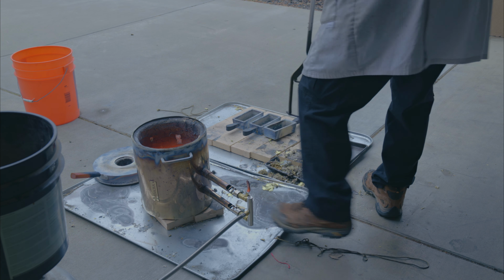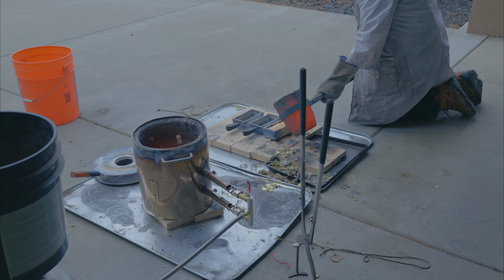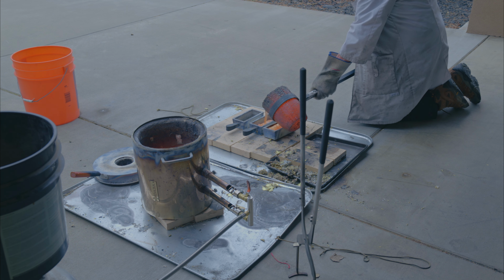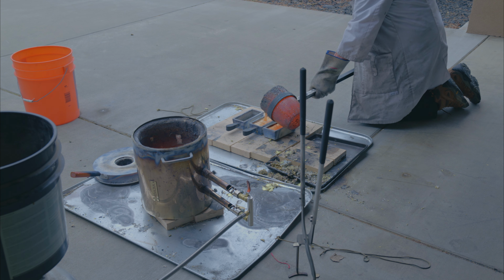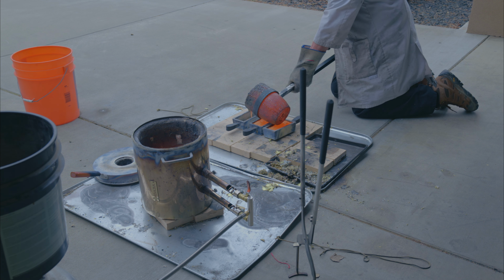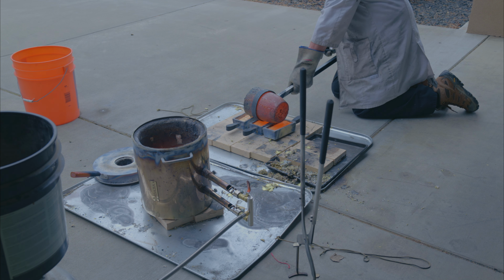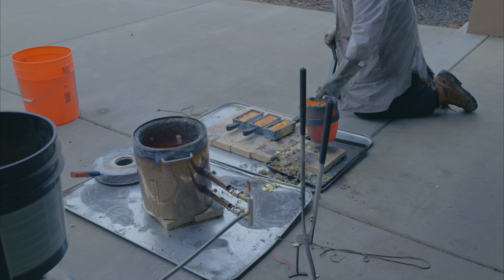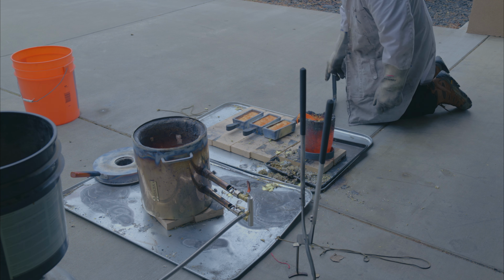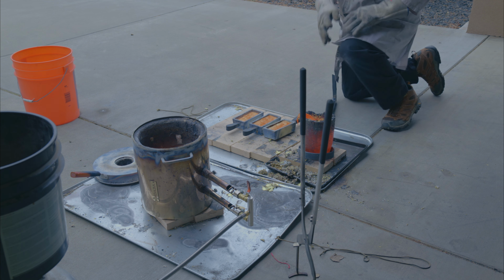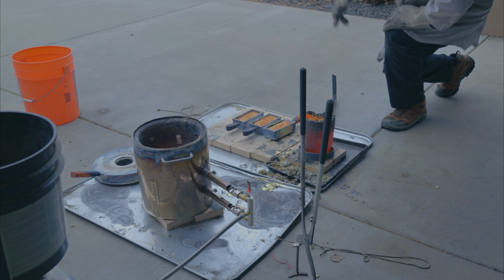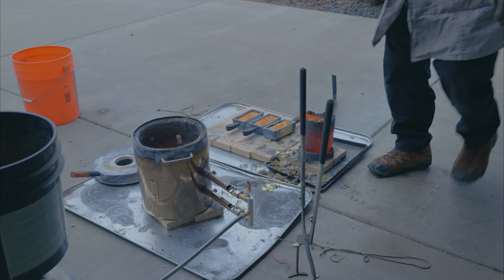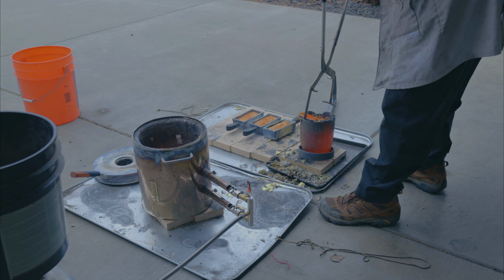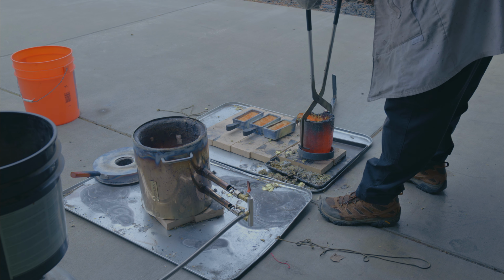Don't overfill the ingots. They only need to go up near the top. It makes them easier to get out if there's a little gap between the top of the brass and the top of the sides of the mold. Because I'm going to melt some more brass, I'm going to pick up the crucible, put it back in the furnace, and go ahead and recharge it with fresh cartridges and keep going.